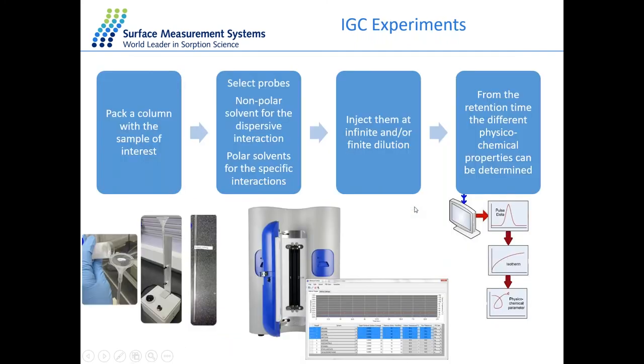So some basic procedure to perform the IGC measurement. We first need to pack a column with a sample of interest. We need to select different probes for different interactions: the nonpolar probe for the dispersive surface energy and the polar probes for the specific interactions. We can then inject all the probe molecules at different concentrations. And from the detecting signal, we can then calculate the surface property of the solid inside the column.